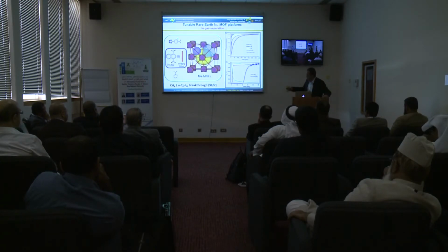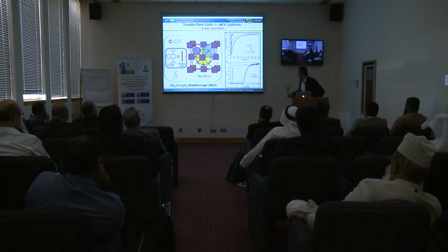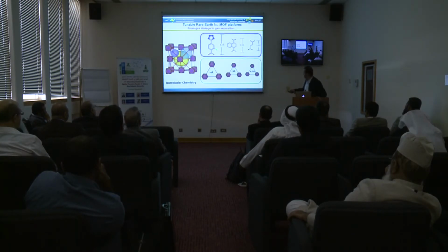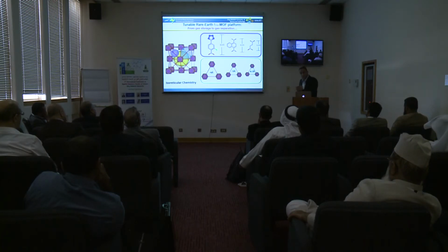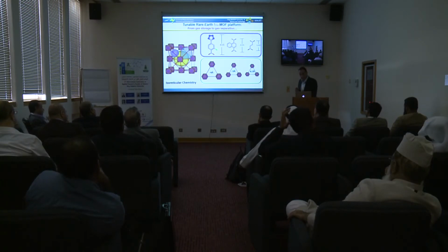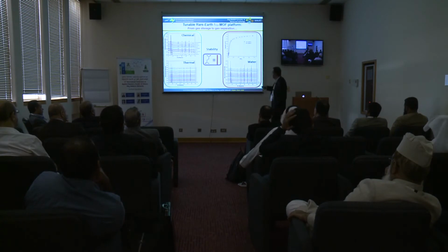So again here, just to summarize, you can control the width of your triangle. You have what's called kinetic diffusion of molecules, meaning molecule can go in slower and faster. But if we reduce this further, we put, for example, fumaric acid, we reduce the pore size to this size. And here, this is the first time that you can see this in a porous material. What we have now is a control of how molecules can diffuse. And interesting enough, this material is stable in water, chemically, and so on.